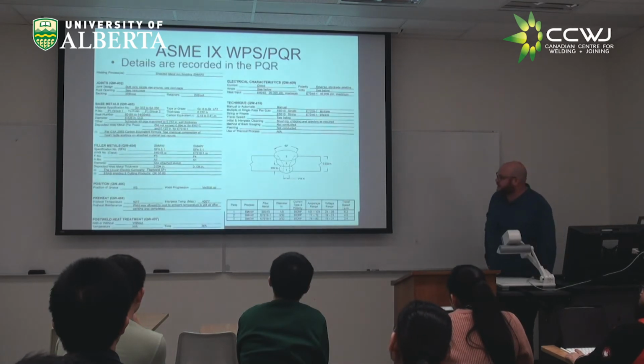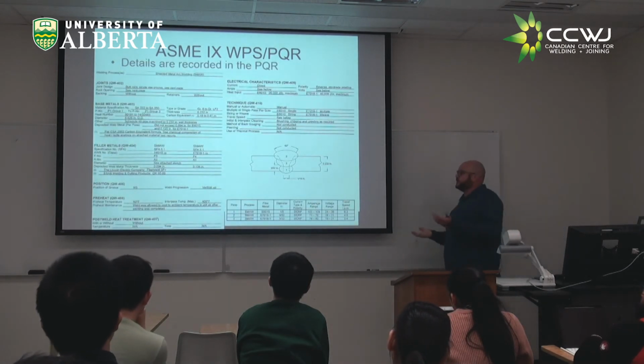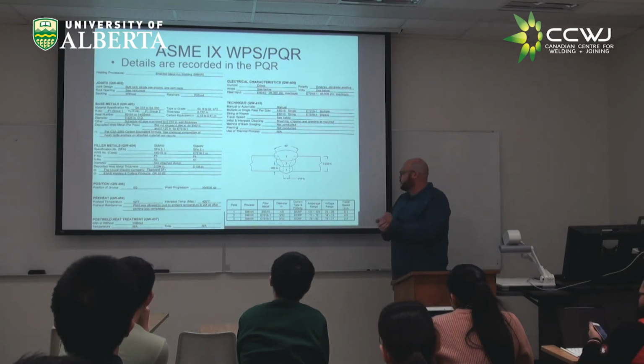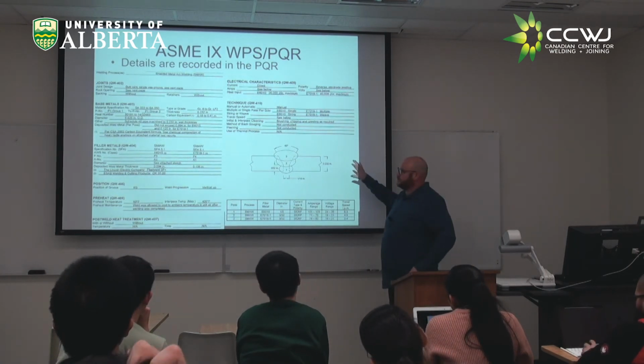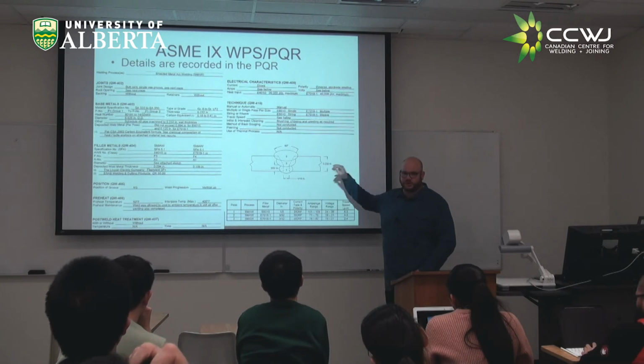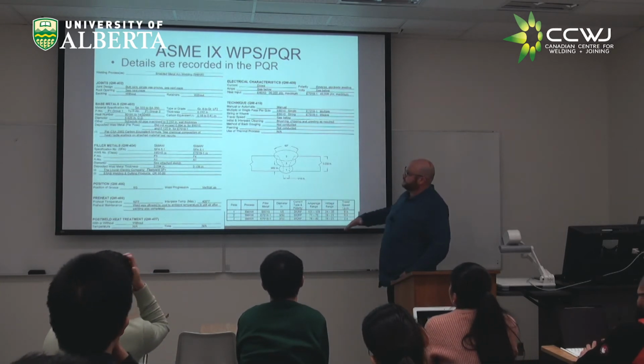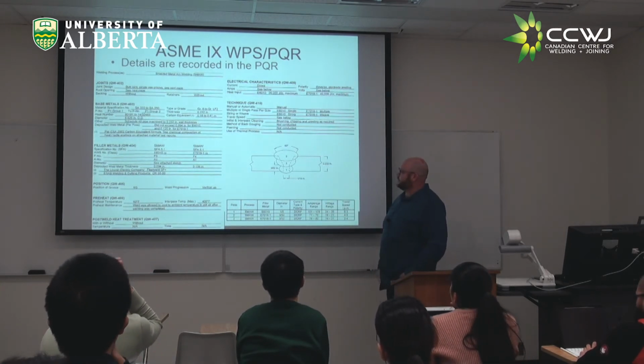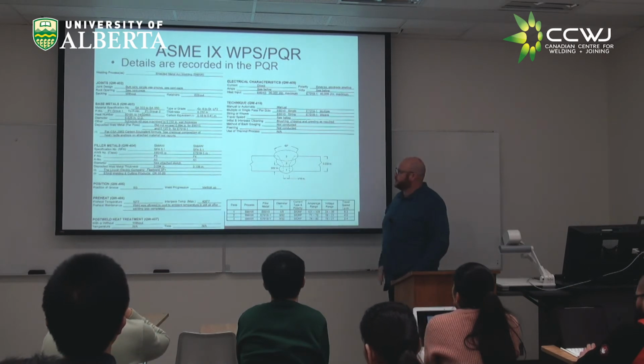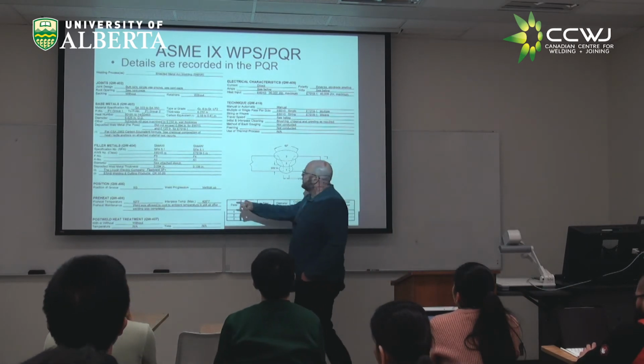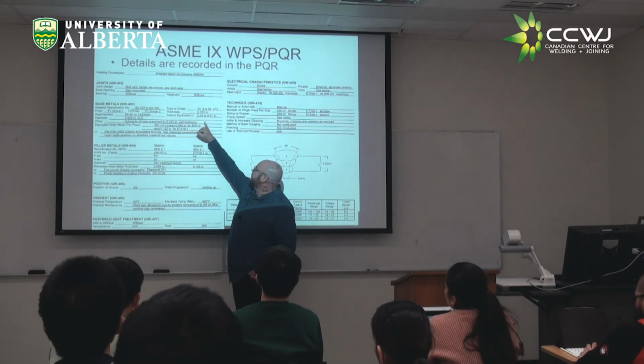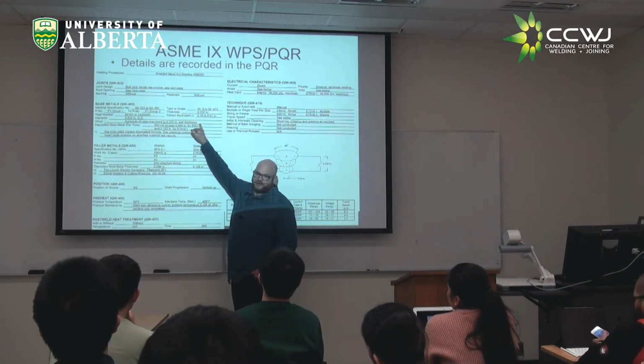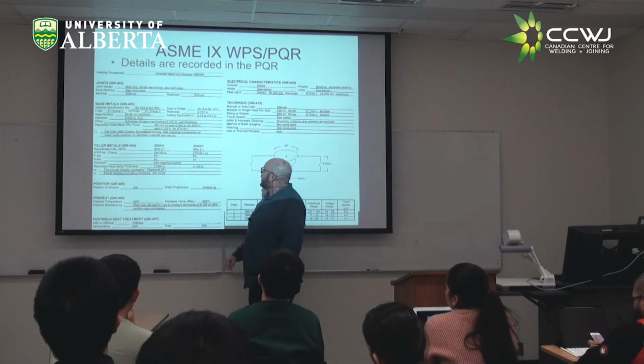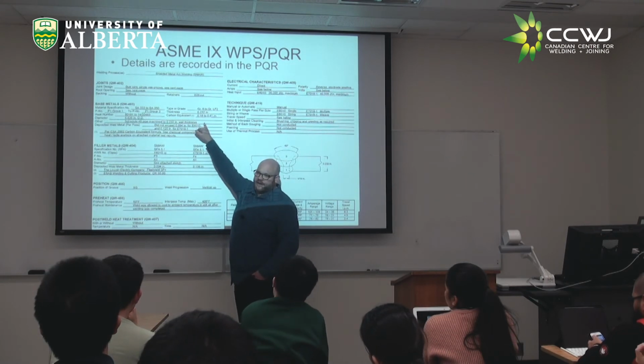So once all that's done, basically you start to populate your PQR. And PQR, as I said before, these are the actual ranges of variables that were used during the actual welding. This is a real PQR. It's basically one of the more generic ones. But you can see they listed everything right down to the carbon equivalent, which again, ASME doesn't care about the carbon equivalent unless you're doing a temper bead weld. But there's lots of other codes and standards that do.